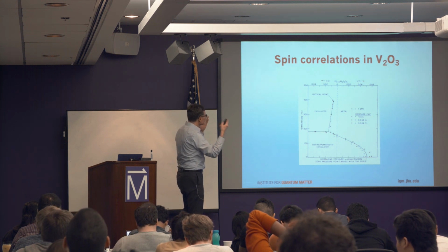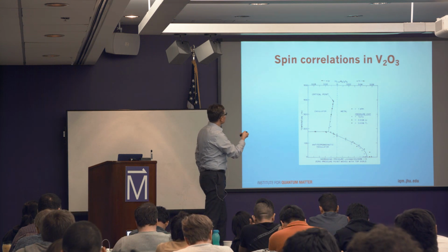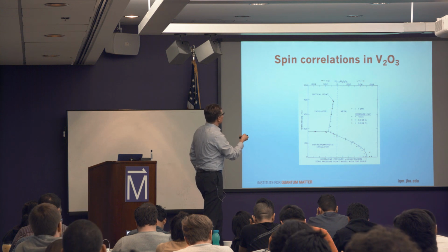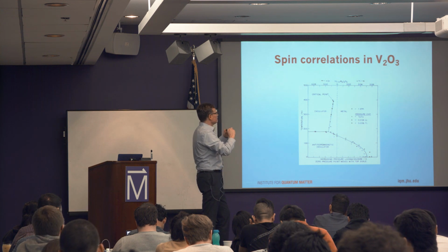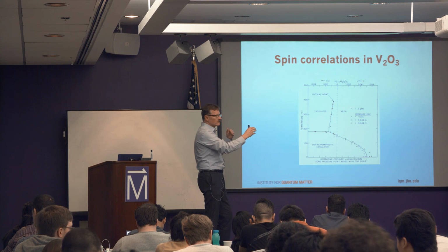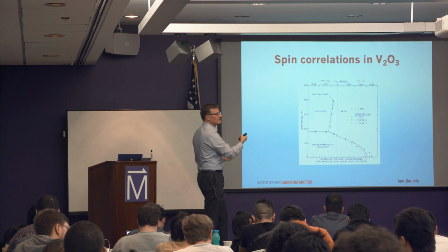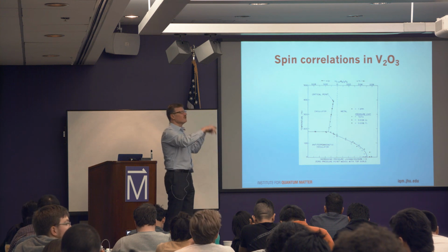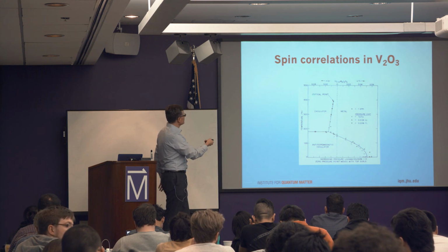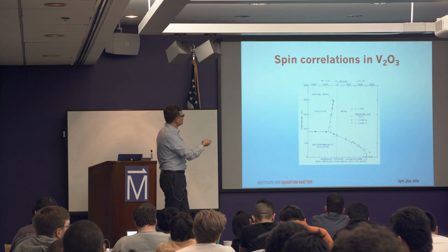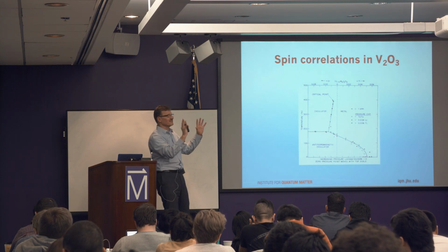And so the concept that has been proposed is that this is effectively reducing the Coulomb repulsion, and so driving it more towards a metallic state. And this is increasing the Coulomb repulsion, and therefore localizing the electron, so it becomes a Mott insulating state. And so this phase boundary is the transition as a function of U over W, supposedly.